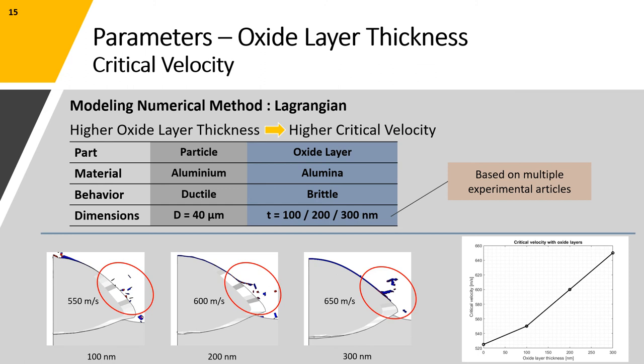Our model was able to predict a realistic behavior in which the critical velocity of the particle increases as does the thickness of the oxide layer and also the breaking of oxide layer initiates at the outer edges of the particle upon impact.